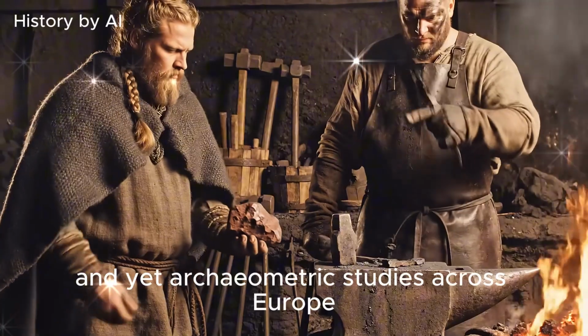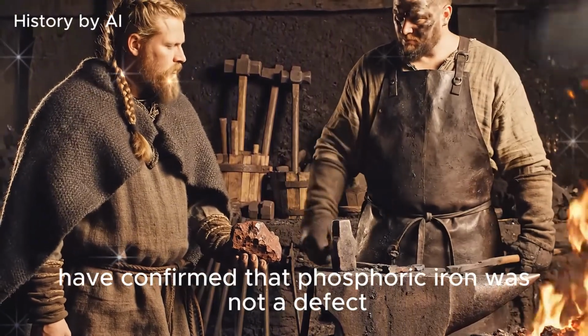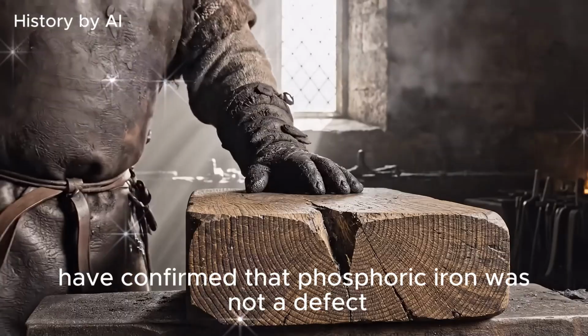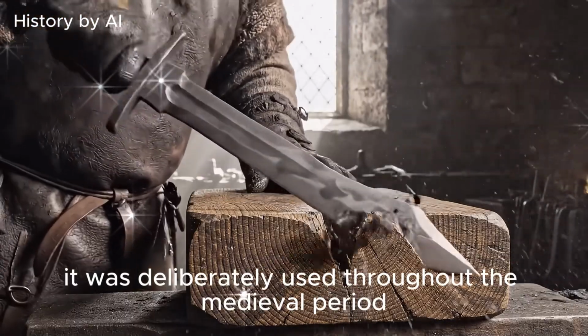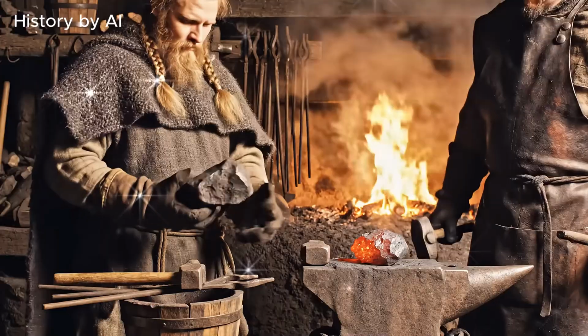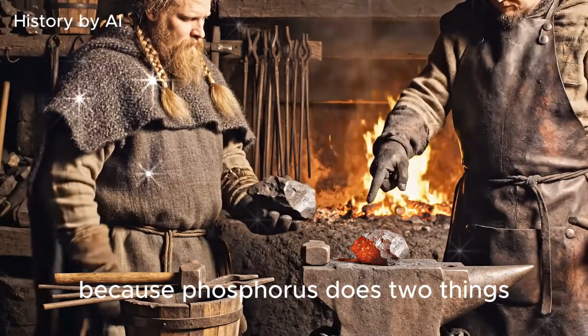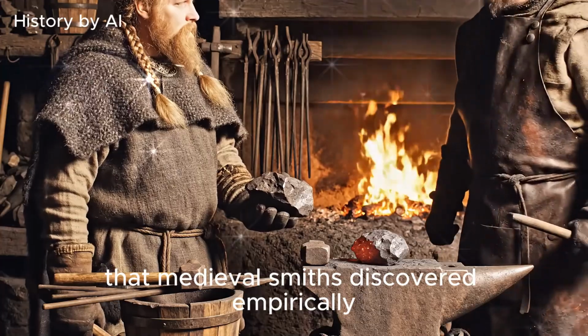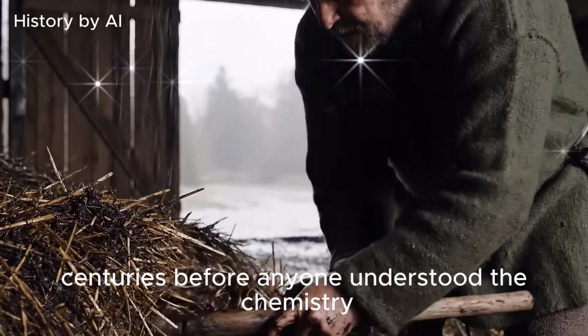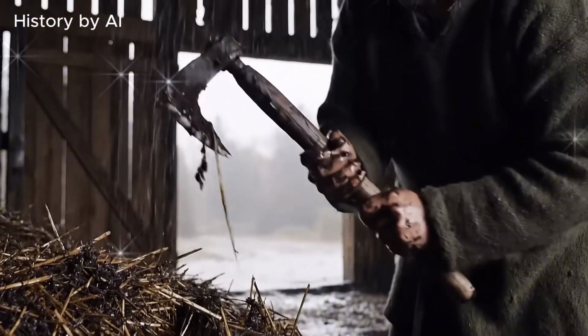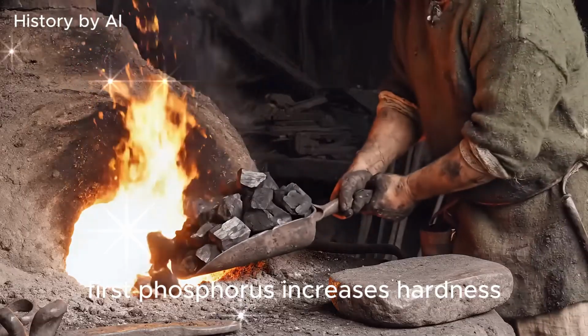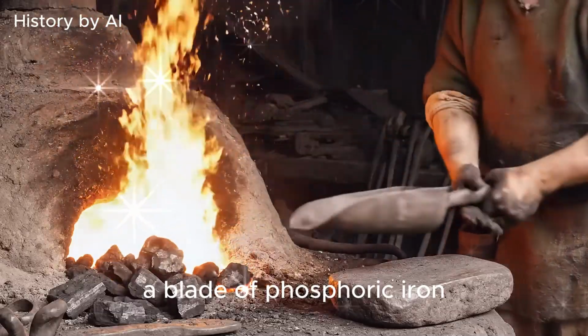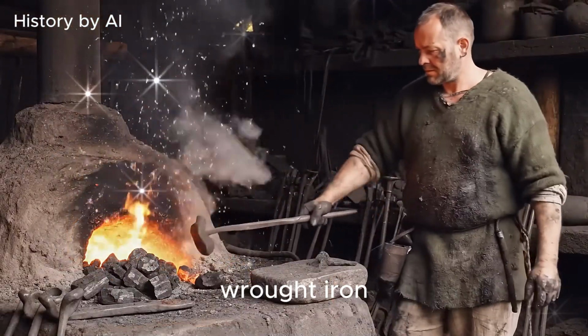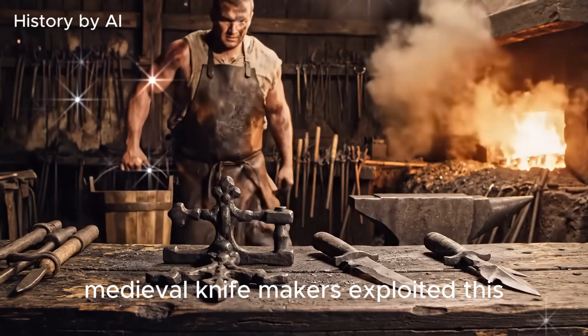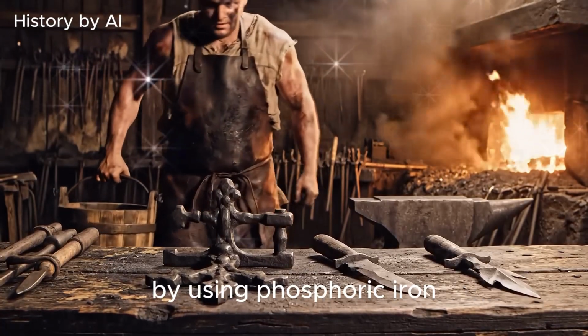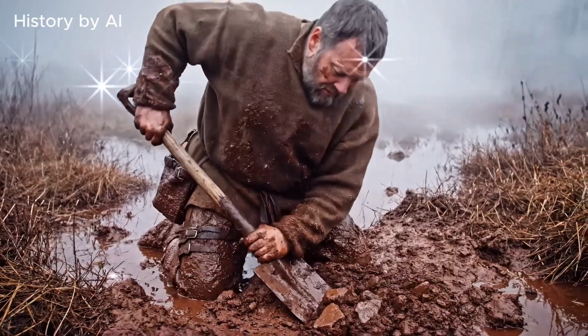And yet, archaeometric studies across Europe have confirmed that phosphoric iron was not a defect. It was deliberately used throughout the medieval period. Why? Because phosphorus does two things that medieval smiths discovered empirically, centuries before anyone understood the chemistry. First, phosphorus increases hardness. A blade of phosphoric iron holds an edge better than pure wrought iron. Medieval knife makers exploited this by using phosphoric iron specifically for cutting edges.